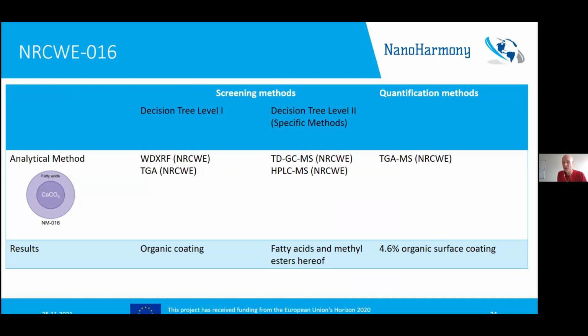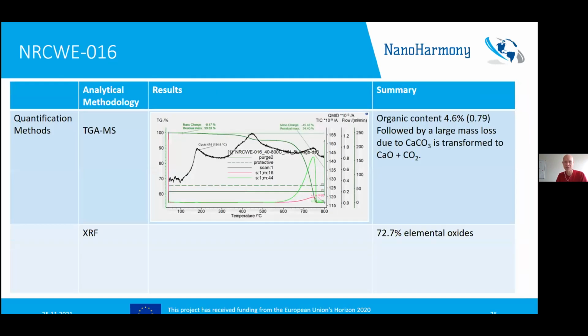Then we have the calcium carbonate, and this is an example of how analyzing the surface chemistry is not that trivial, because if we look at the organic coating using TGA-MS, we would see quite a big mass loss. But if we dig further into the spectrum, we see that about 5% of the mass loss occurs at a medium temperature, and then as we go to 600 degrees, we have an even higher mass loss. But this mass loss is not attributed to the organic content. It is in fact attributed to calcium carbonate being transformed to calcium oxide, which decarboxylates. So you also need to be a chemist in order to interpret the results, and you cannot use them blindly.